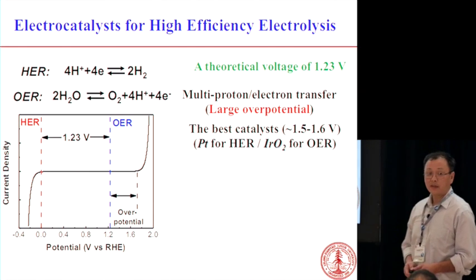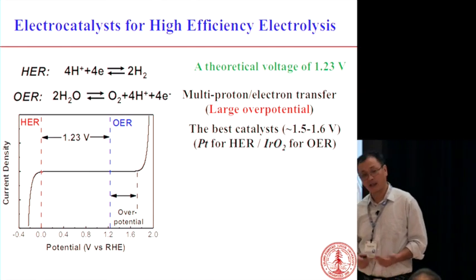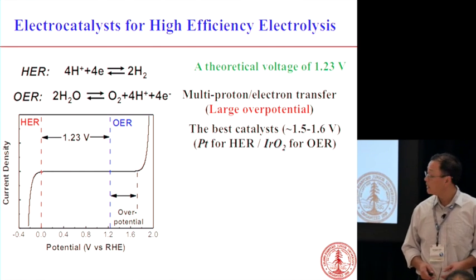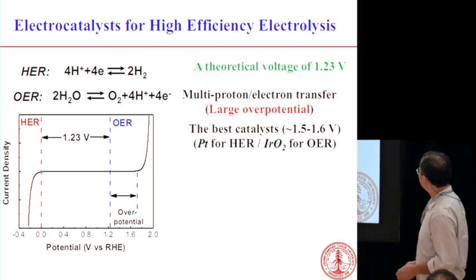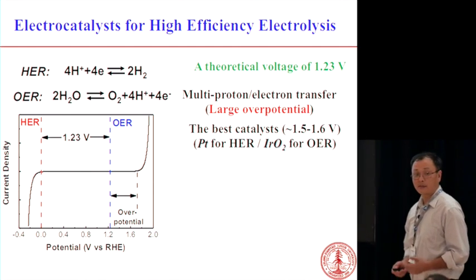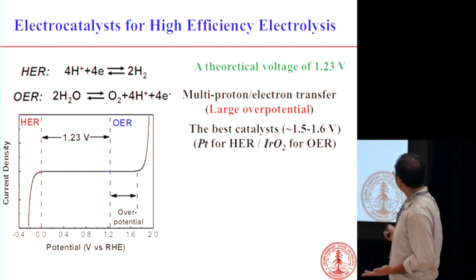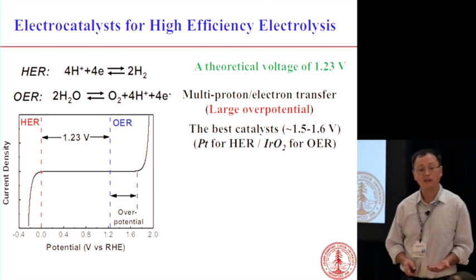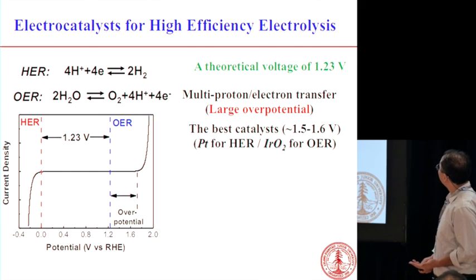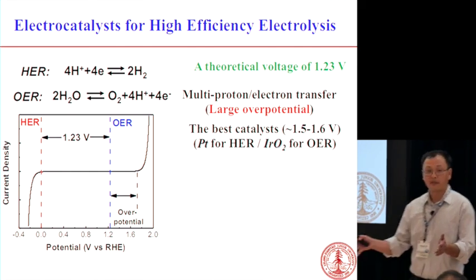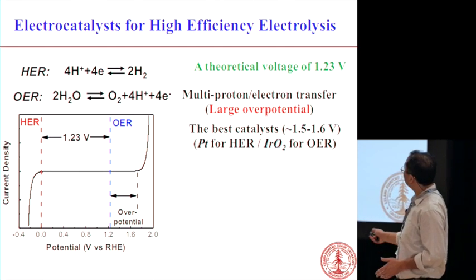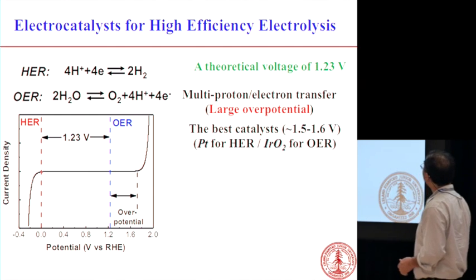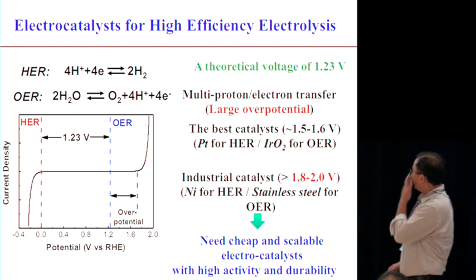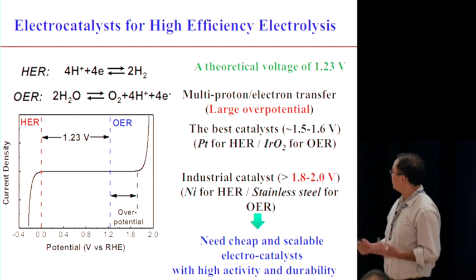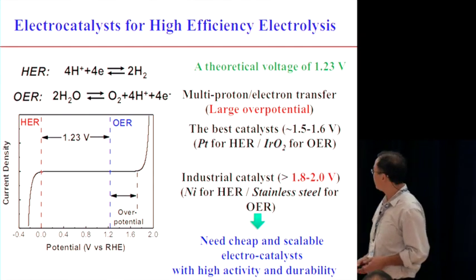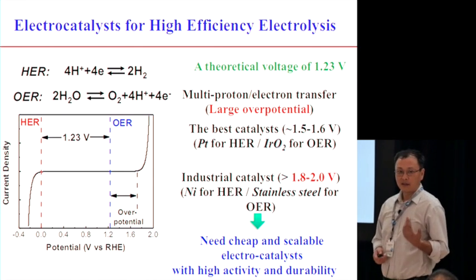So for these reactions, typically you would need a precious metal as the catalyst to get very high activity, to lower the overpotential. For the hydrogen side, platinum is typically the best catalyst, and for the oxygen side, iridium oxide is the best catalyst, okay? In that case, you would be able to get 1.5 to 1.6 volts to get these two reactions to happen simultaneously. And in industry these days, for water splitting in basic solutions, in order to lower the